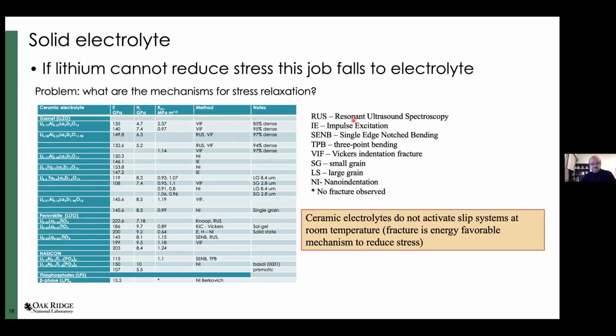And this table here, okay, let me go back. How do we measure resistance to fracture in the mechanics world? By measuring fracture toughness. This is this parameter here called K1C, which indicates the critical stress intensity factor required to propagate an existing crack. So you have a very sharp crack inside the material. You keep loading the material until that crack propagates to failure, and that's your fracture toughness.